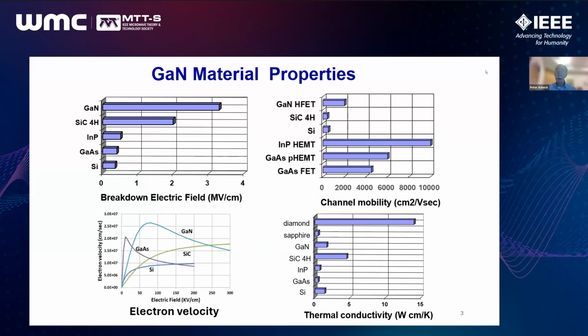Of course, gallium nitride is endowed with a host of wonderful characteristics, particularly for power amplifier applications. Breakdown electric field at 3.3 megavolts per centimeter is about 10 times that of silicon. Has a channel mobility of 1,000 centimeters squared per volt second in the 2D electron gas form, which is 5 times higher than silicon and on a par with other 3-5 devices. Electron velocity is very high, can exceed 2 times 10 to the 7th centimeters per second, and extends over a very wide range of electric field. And the thermal conductivity, particularly on a silicon carbide substrate, is really spectacular. So these things are well known to almost all of us.